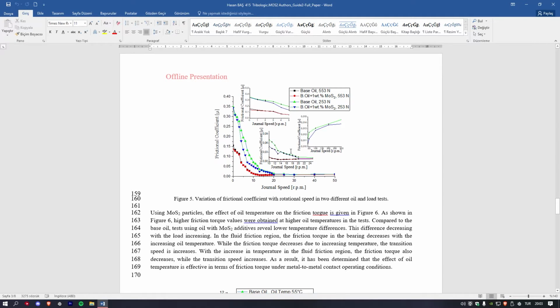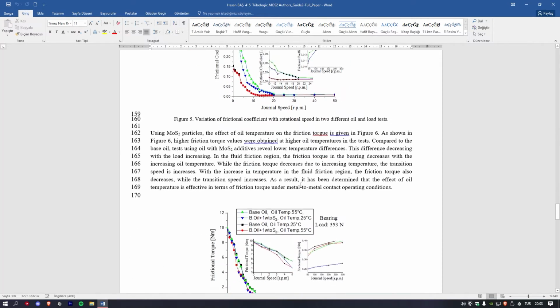In the fluid friction region, the friction torque in the bearing decreases with the increasing oil temperature, while the transition speed increases. With the increase in the temperature in the fluid film friction regions, the friction torque also decreases while the transition speed increases. As a result, it has been determined that the effect of oil temperature is effective in terms of the friction torque under metal-to-metal contact operating conditions.